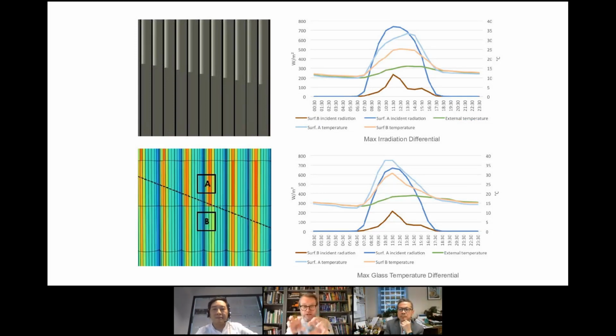So this is a breakout from that. You can kind of see this A and B on the left, and these graphs on the right, which illustrate the difference between the irradiance in the surface of the glass. There's a number of graphs here because there's a number of layers of glass. But if you look at, for example, surface A, which is the big blue curve at the top, it gives you a certain time of day when that is maximum, and you'll note that it doesn't necessarily coincide with the maximum ambient temperature. So in many ways, one offsets the other slightly.